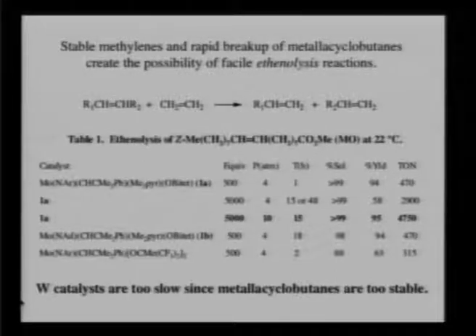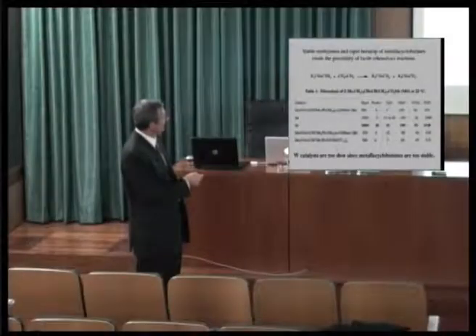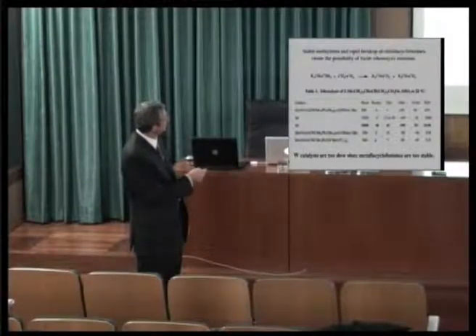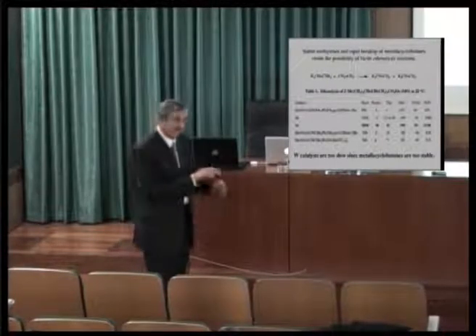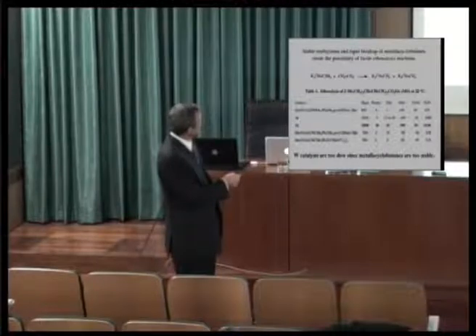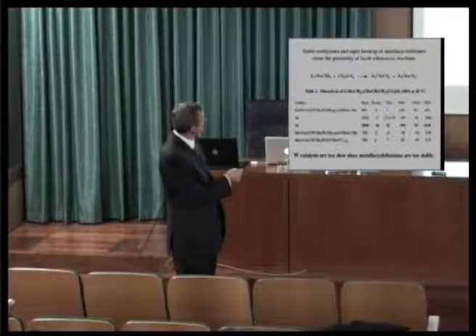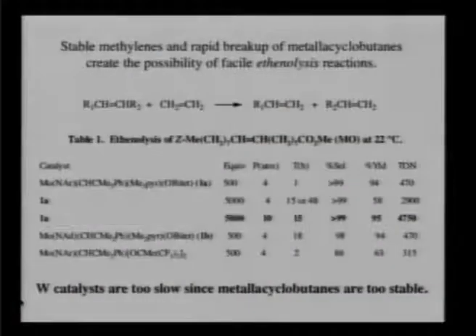So it's a C18 with the double bond approximately in the middle. Well, it is in the middle, and this happens to be a methyl ester in this case. So you can run the reaction backward. You can put in 5,000 equivalents of methyl oleate with the type of catalyst that I've been talking about, the molybdenum biphenolate catalyst, the chiral one. And you can, at 10 atmospheres at room temperature, I don't think it needs 15 hours, get a greater than 99% selectivity to 1-decene and methyl 9-decenoate in a yield of 95%.